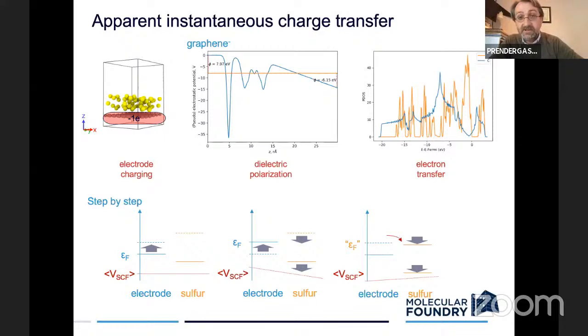Now, suddenly the potential at the surface will jump up to try to match it, to do what a metal would do, which is the image charge screening. And that sudden increase in the electric field between those two objects would actually accelerate this process. And you have even less control in that sense if you do molecular dynamics at constant potential, because any